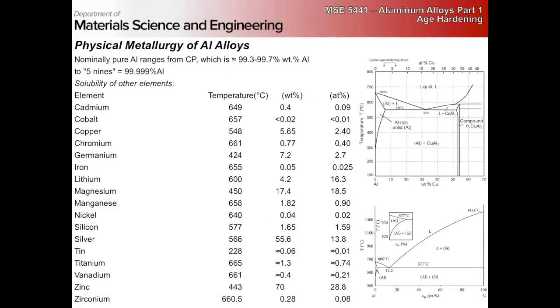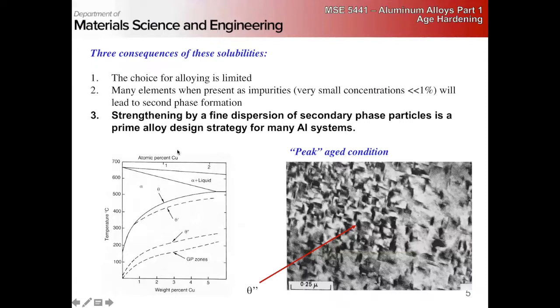Right, we talked about how in aluminum alloys, the choices for alloying elements are pretty low because of the low solubilities of a lot of systems, a lot of elements, except for our major alloying ones, such as copper, lithium, magnesium. Right, silver has a lot of solubility, but we don't exactly use aluminum silver alloys for anything, and zinc. And the consequences of those low solubilities is that we don't have a lot of choices for alloying, and many elements, even at impurity levels, are going to lead to secondary phase formation in intermetallics.